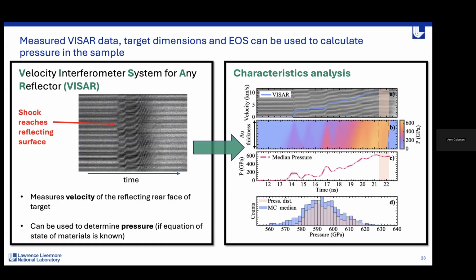Through Lagrangian sound speed and particle velocity relations for each of the layers, we can integrate the characteristics equations backwards and work out the pressure in the sample during the probe time. This reconstructs the stress particle velocity states throughout the target as a function of both time and position, accounting for any interactions or interfaces between the layers and the targets. And so from this, we're getting the pressure.